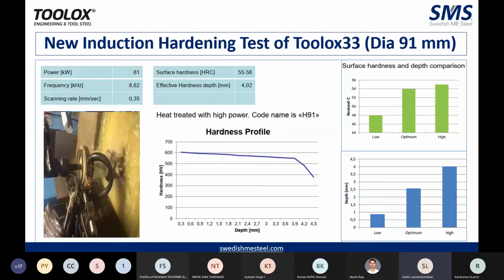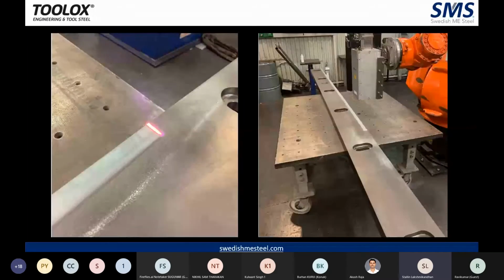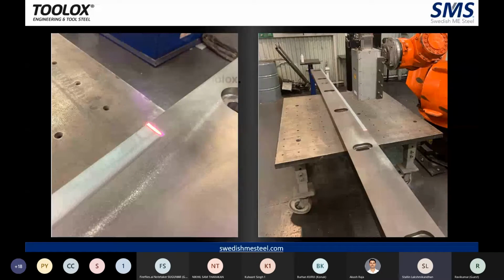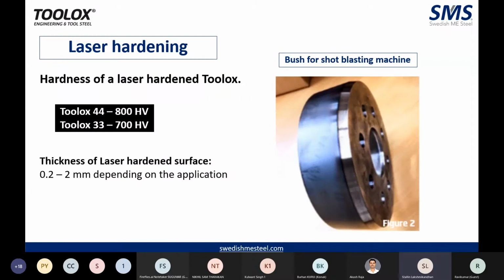So this is also another process, which is an upcoming, innovative and exciting process called laser hardening. This is a technique wherein you will be able to increase your case depth of 0.2 to 2 mm. When it comes to Toolox 44, you can improve up to 800 HV, and Toolox 33 you can go up to 700 HV.